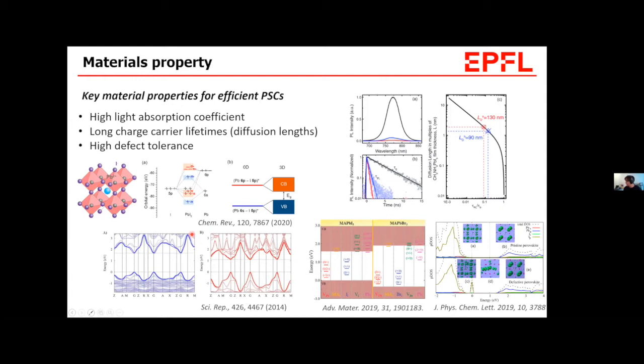This optical property is actually based on the electronic band structure of perovskite. In perovskite, the band structure is primarily determined by the BX6 octahedra, for example, PbI6. But the contribution of the A-site cation to the electronic property is not very significant, because the electronic levels of the A-site cation lie deep inside the valence and conduction bands. So it does not make a great impact on the electronic band structure.